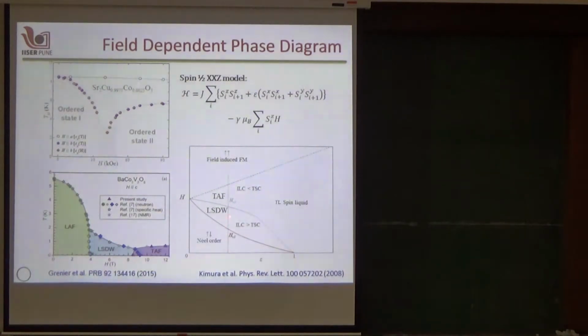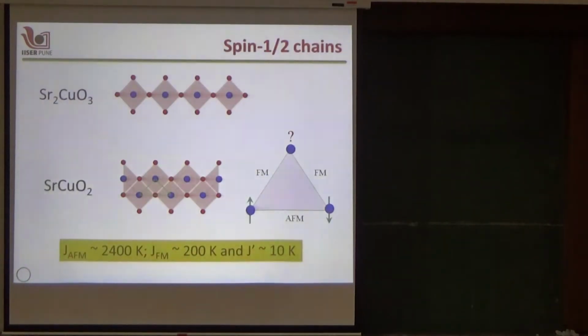Now whatever I have understood so far is that in the TAF, these longitudinal correlations are weaker than the transverse correlations, which is always the case, and that is why in the pristine chain and in the zinc doped chain, the transition temperature was increasing with increasing magnetic field. Whereas in this region, the longitudinal correlations are stronger than the transverse correlations, and that's why you get a phase sandwiched between these two, which is known as the longitudinal spin density wave phase. So if this is true, then low temperature measurements should reveal this.